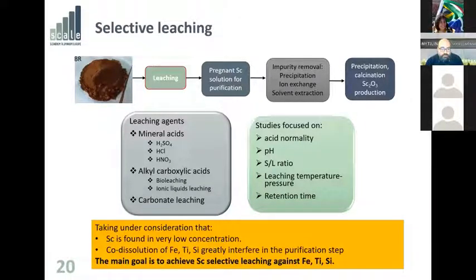So here, the most important thing to look out for is that since we're having scandium in a very low concentration, we need to avoid the co-dissolution of the major elements like iron, titanium, and silicon, because they will interfere in the next step of the purification process. Silicon will not only interfere in the purification process, but it could lead also to gel formation. Iron and titanium have close relations to scandium and will most likely be co-extracted during the impurity removal step. Therefore, you need to achieve a selective leaching against iron, titanium, and silicon.